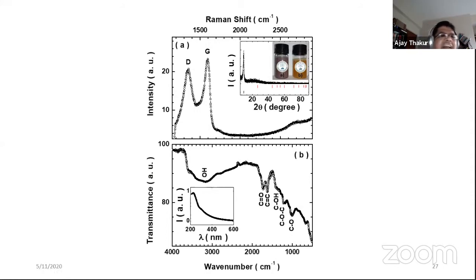Not only that, any kind of defect which exists in the basic carbon layer is also captured by this D peak. So this D-G like structure was characteristic of a very high quality graphene oxide reported by the earlier methods, like those which unfortunately had explosive nature.